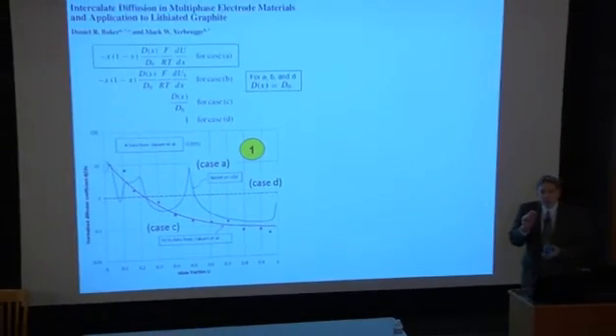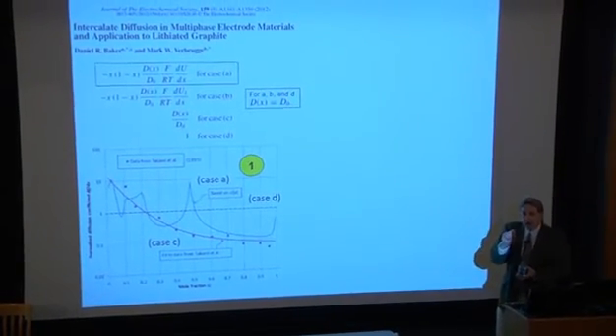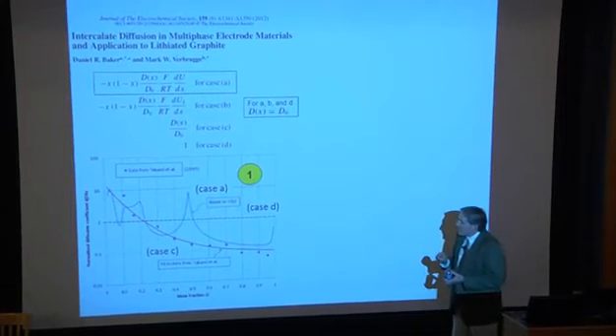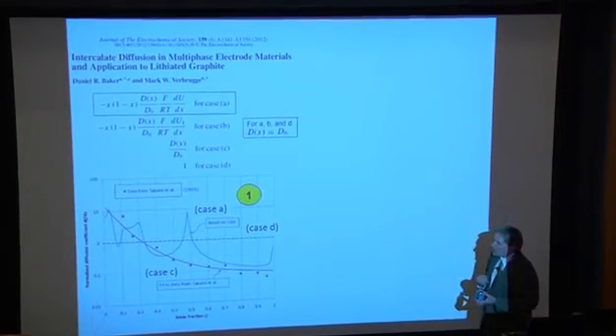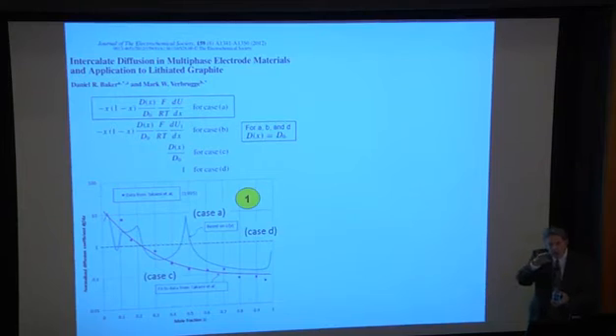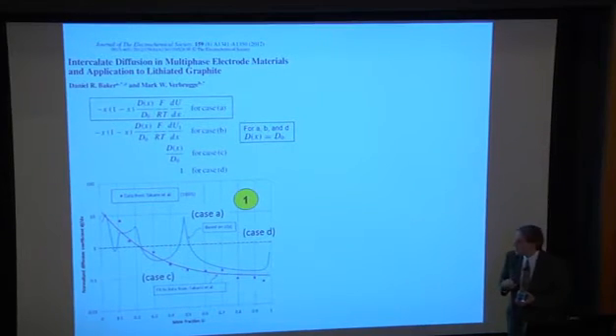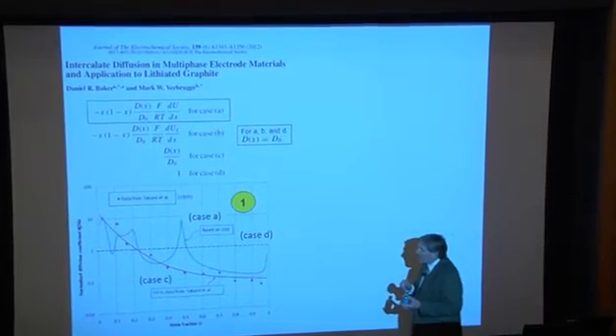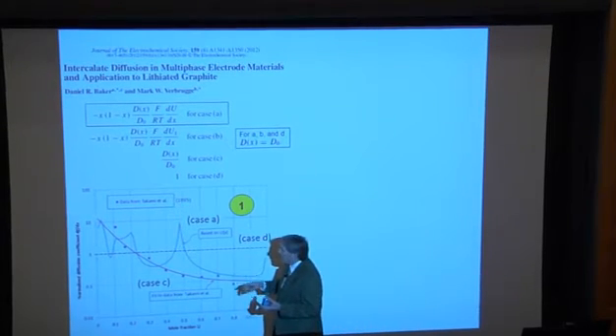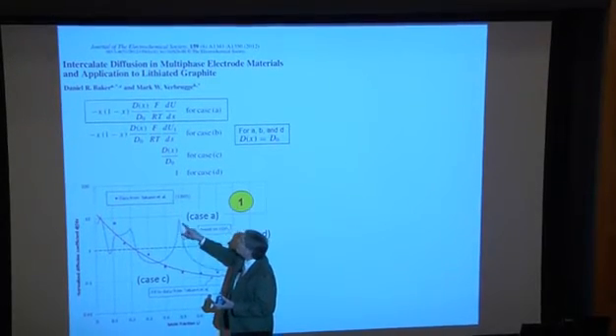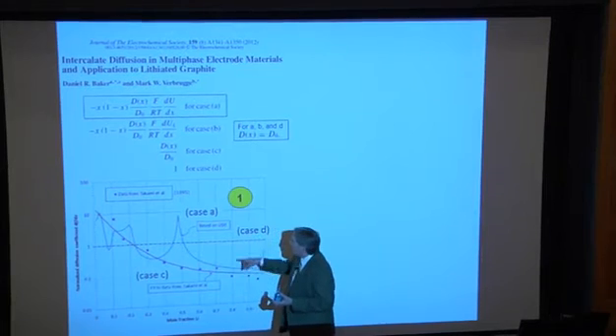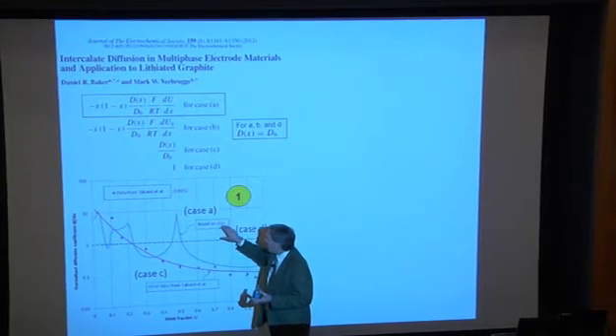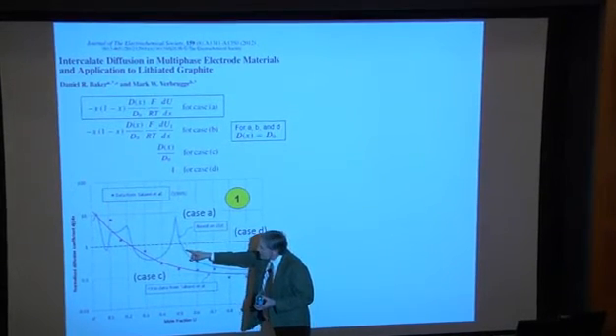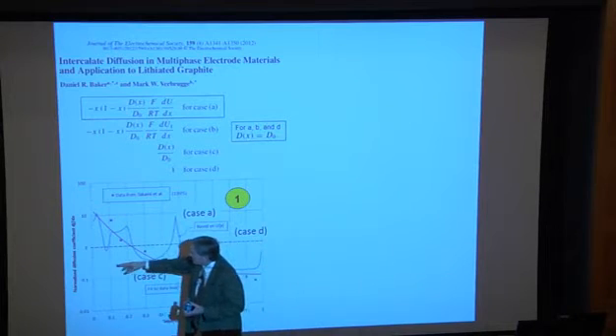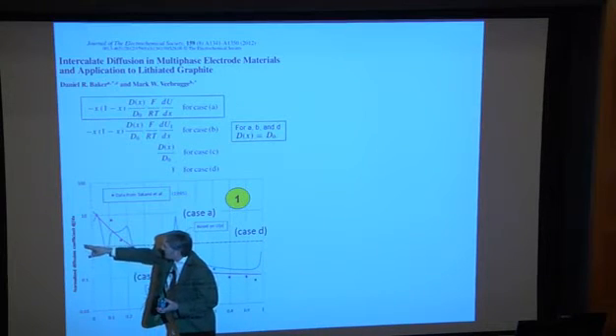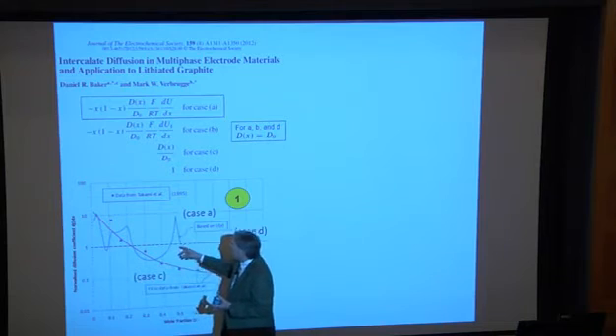So my thought was, let's apply it to graphite, and hopefully we can go right to the open circuit potential. I'll show an open circuit potential curve in just a minute, but it has this disordered nature that provides the energetics for this dU/dx term. So when we were doing this, what we found is we started computing, this is case A above, based on this open circuit voltage that we differentiated, computing these diffusion coefficients. So over here it's the normalized diffusion coefficient, normalized by its value at infinite dilution.